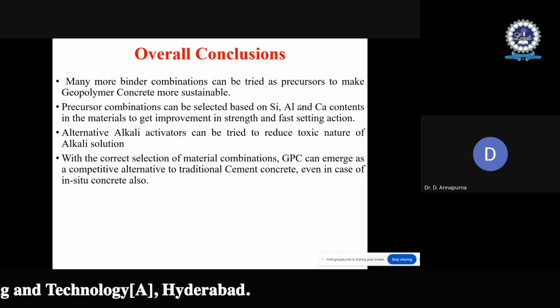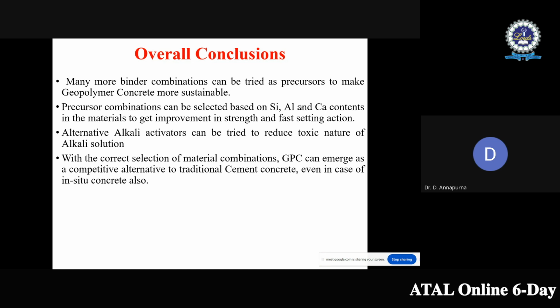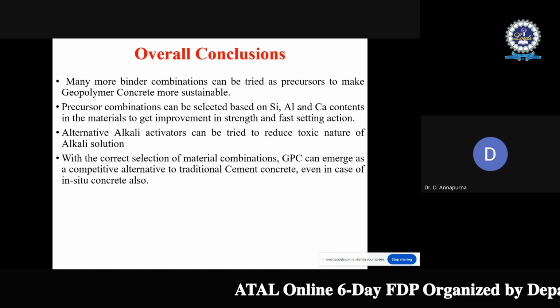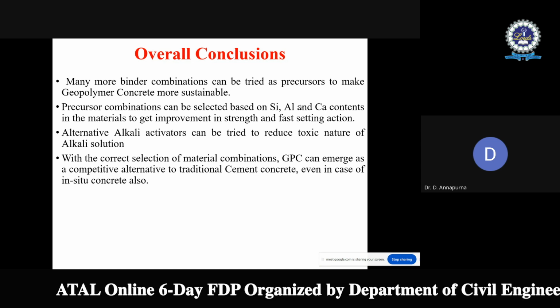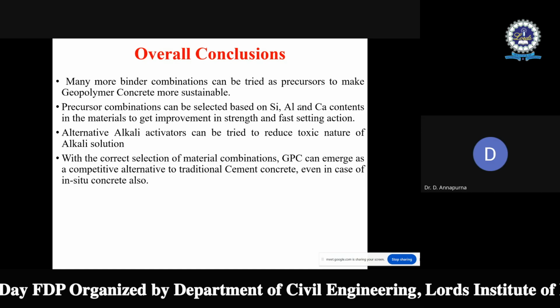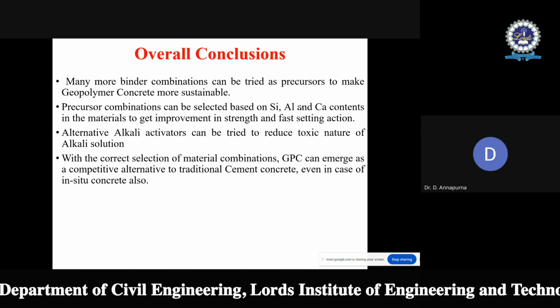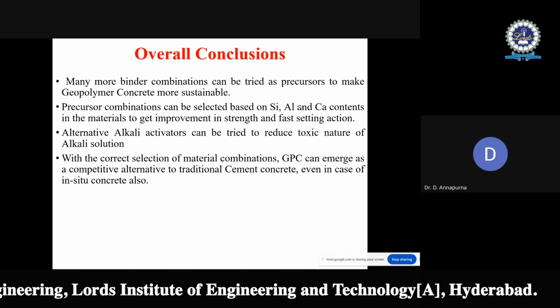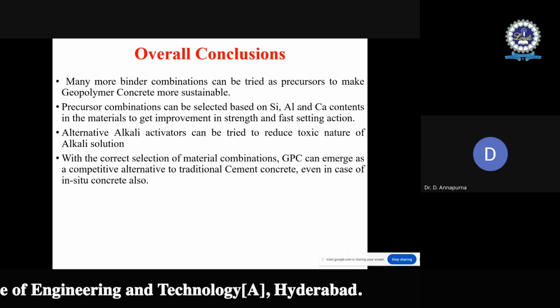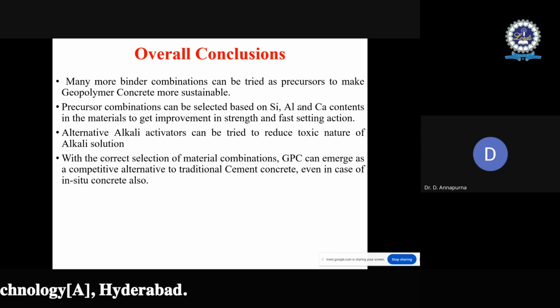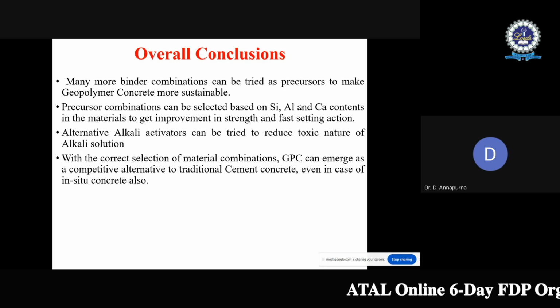Precursor combinations can be selected based on silica, alumina, and calcium contents in the materials to get improvement in strength and fast setting action. And the next one is alternative alkali activators can be tried to reduce toxic nature of alkali solution. I said sodium hydroxide solution was used widely in the preparation of geopolymer concrete, but it is too toxic and it is very costly material. To get again economical and environmental friendly geopolymer concrete, then we can try with other alkali activators.